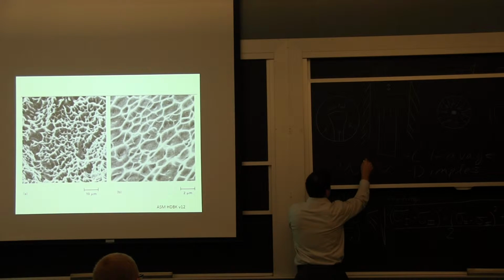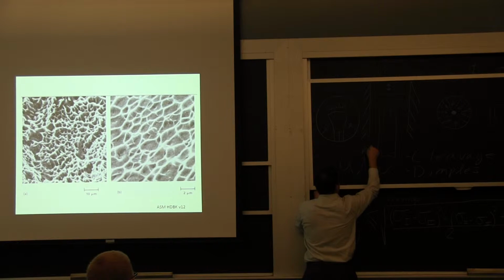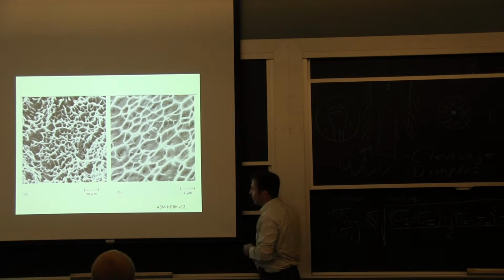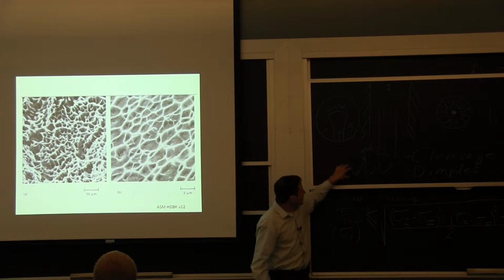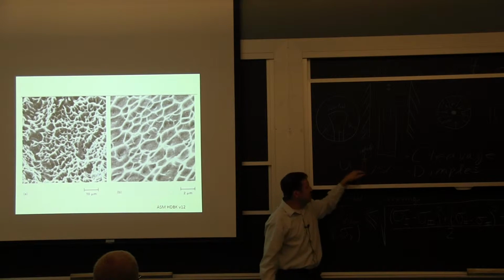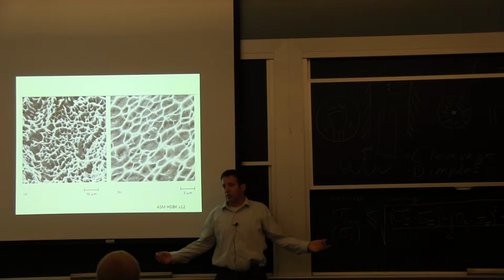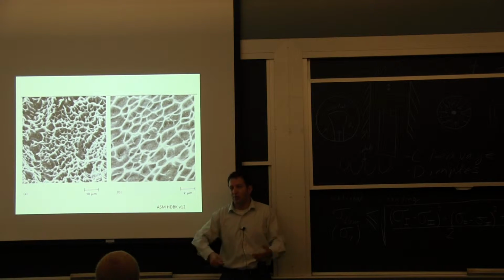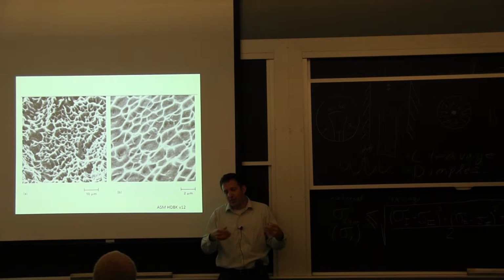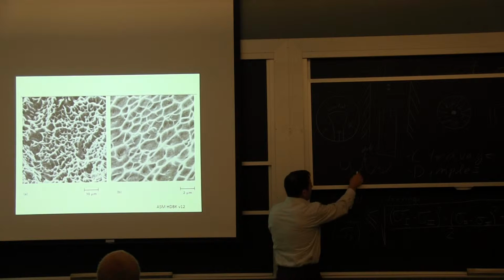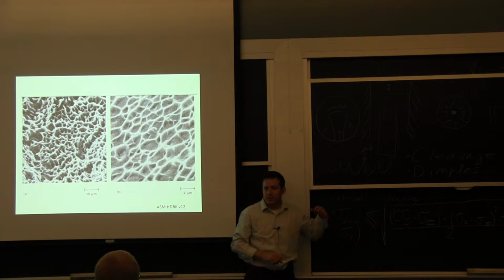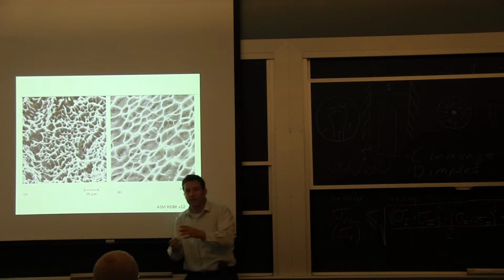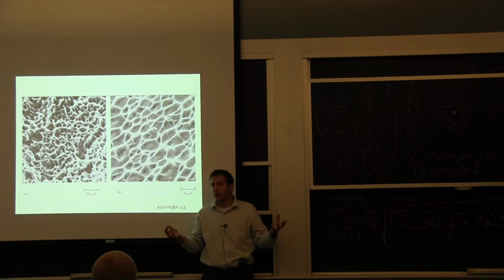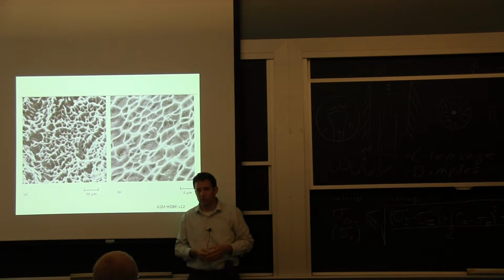So I have a void, and then I have the ligament. That's the white portion because it's got a lot of profile here. And then the grayer or darker portion is the bottom of the hole. So I know that I had to go through all this process and forming these stretches before I broke. So it's very hard to argue any effect of a notch here, because that specific area broke even without knowing that there was another one right here. So it's not even going from one side to the other. It's sort of working its way internally, and then eventually the crack will come right through it.